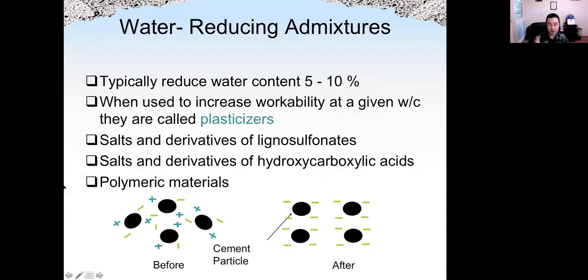So water reducing agent has basically two functions. One is to reduce the water content. If we do not want to increase workability, we want to keep the slump the same, so we can reduce the water content by a certain percentage. In that way we can increase the strength of concrete. Or we use it to increase the workability and keep the same water to cement ratio, which means we do not change the water cement ratio, but by adding these chemicals we increase the slump. In that case we call that plasticizer. Most of the water reducing agents are organic matters, as we can see from here.